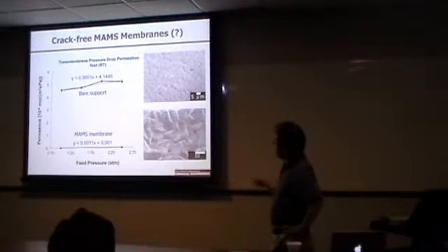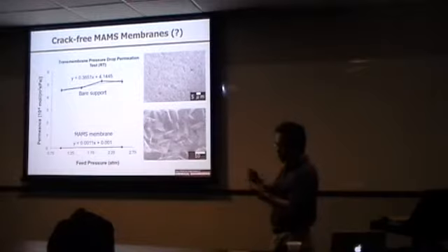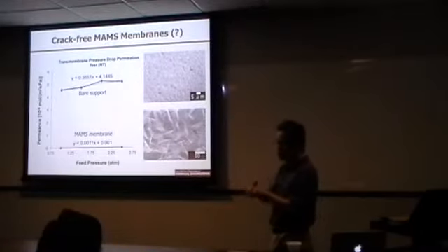And then my student came up with basically an idea. Take a look at the sol-gel chemistry literature. In order to prevent the crack, what they're doing is they add surfactant. So what the surfactant does is it will reduce the surface tension.